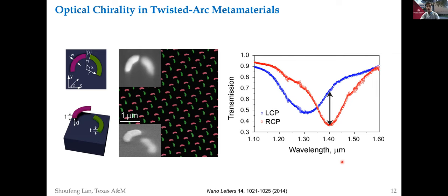For comparison, I want to remind you that the optical rotation for natural chiral material is around 1 millidegree. So our chirality is more than 4 orders larger than that in natural materials. Not to mention that the thickness of our chiral metamaterial is less than 200 nanometers.